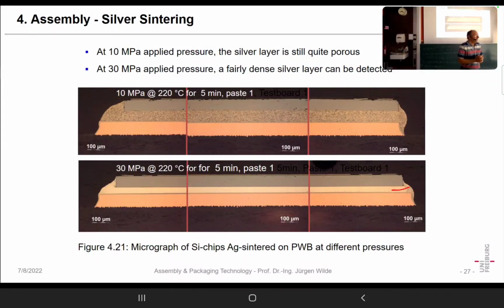Fatigue life is almost 10 times better than for soldered joints. And that's one of the reasons why sintering is used nowadays for power electronic modules. Here you can also see that in areas where there is no or less pressure, the material is less dense than in the high pressure zone.